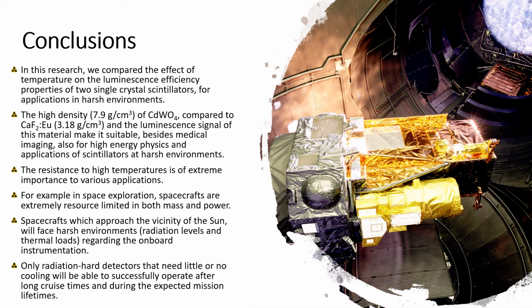The high density of cadmium tungstate compared to calcium fluoride doped with europium and the luminescence signal of this material make it suitable, besides medical imaging, also for high energy physics and applications of scintillators in harsh environments. The resistance to high temperatures is of extreme importance to various applications. For example, in space exploration, spacecrafts are extremely resource limited in both mass and power. Spacecrafts which approach the vicinity of the Sun will face harsh environments regarding the onboard instrumentation. Only radiation-hard detectors that need little or no cooling at all will be able to successfully operate after long cruising times and during the expected mission lifetimes.